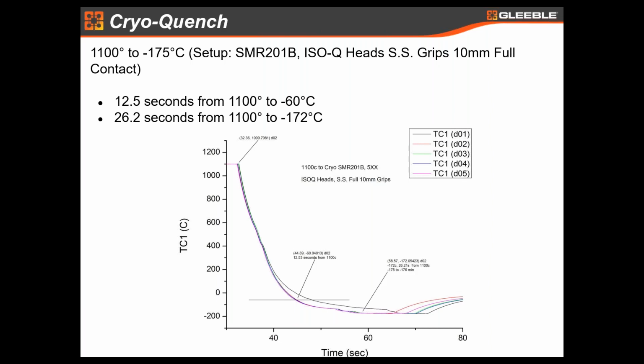We went down from 1100 down to -60 C in 12.5 seconds, and in 26 seconds we went down to -172. So I think that's pretty impressive. I will say it's important to note that the goal of the Cryoquench system is to achieve low, cryogenic temperatures. This can be done quickly.